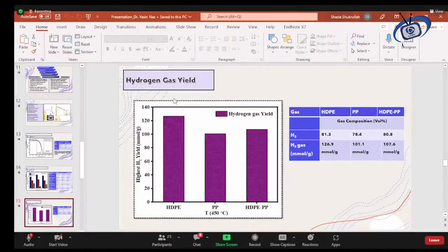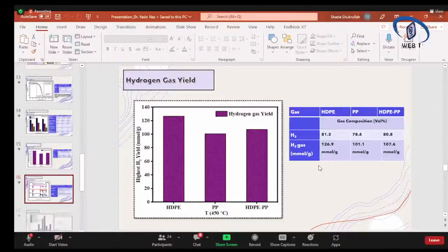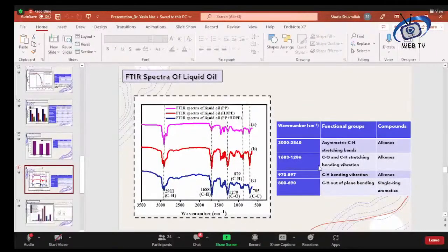So then the gases we get during this process, we analyze these gases to check their composition, and we find that this gas consists of 81.3% hydrogen when HDPE was used as a feedstock, and 78.4% hydrogen when PP was used as a feedstock. And this figure slightly improved to 80.8% when we use a mixture of HDPE and PP. It shows that the hydrogen content was almost similar in all three cases. However, the HDPE shows slightly higher hydrogen content as compared to the pure PP and its mixture with HDPE. Okay. So the oil product was a thick wax form.